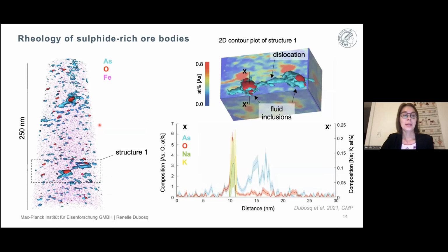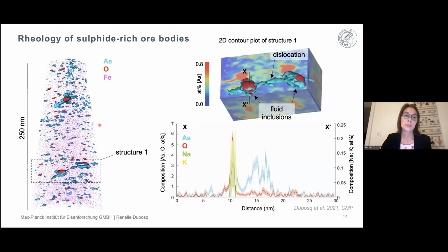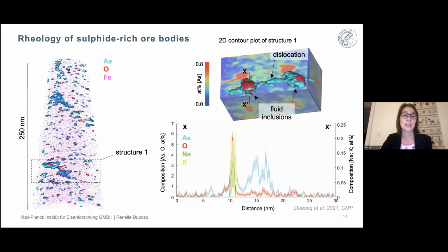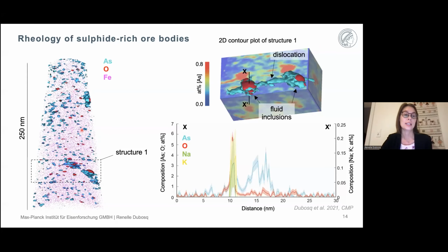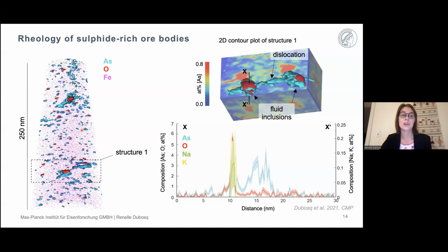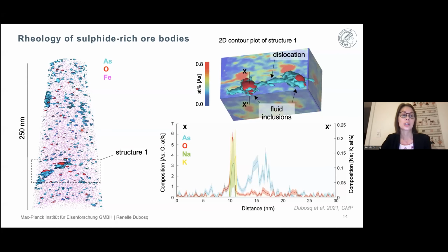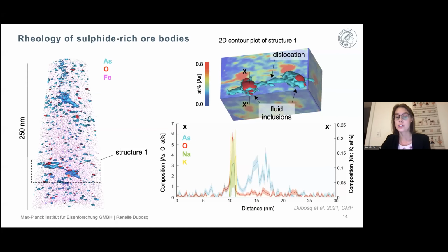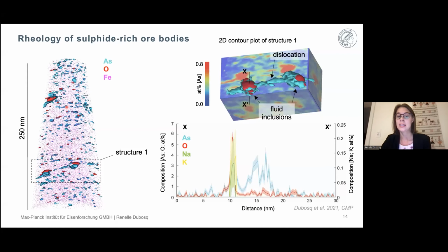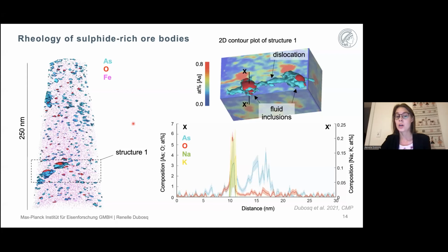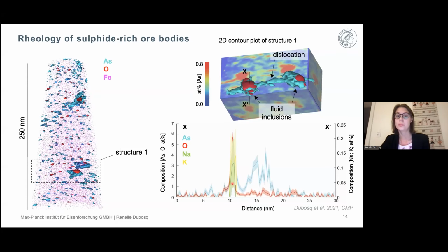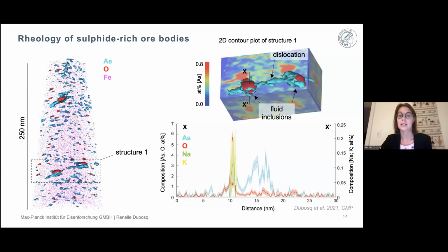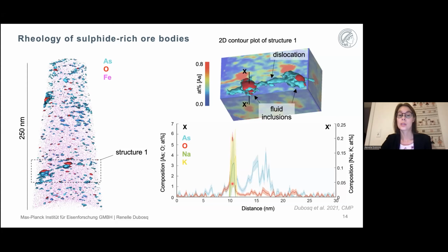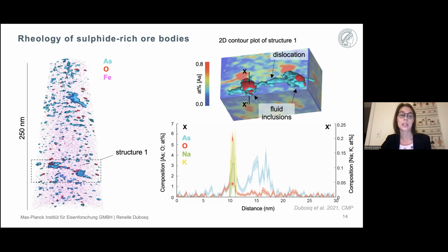So here, the animation on the left shows the 3D reconstruction of the specimen. Once again, the pink dots represent iron ions, whereas the turquoise isosurfaces represent arsenic and red isosurfaces represent oxygen. And we notice in this reconstruction that once again, we have all of these arsenic and oxygen enriched clusters. And if we take a composition profile across one of these clusters, or these features, we notice that there's also enrichment in sodium and potassium. So sodium and potassium are common elements that are found in aqueous brines that form fluid inclusions in the context of metallic ore deposits. And so this reaffirms that these features, once again, are truly fluid inclusions.